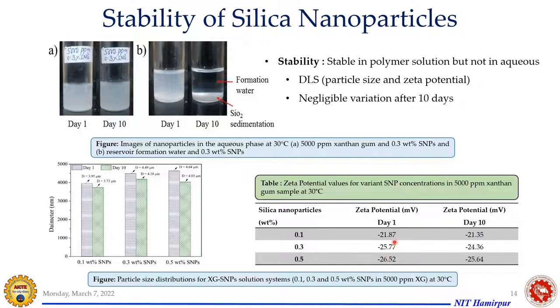Typically plus or minus 30 mV is the value that predicts the stability of nanoparticles, but we could not achieve that. Why? Because the aqueous phase that we used contains a lot of divalent ions. This is the formation water, which has divalent ions collected from the reservoir. Because of these divalent ions, the zeta potential value is affected, and that's why the plus or minus 30 value could not be achieved. But through this visual observation and the data that we get from DLS, we can predict that the nanoparticles are almost stable in our chemical phase, that is the polymer phase which we have taken here.